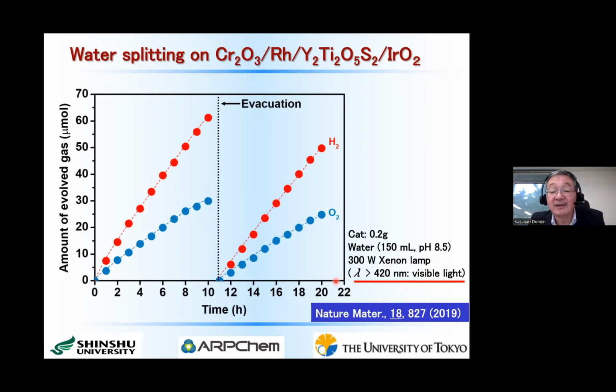However, as you see here, when we continue the reaction for 20 hours, the activity decreased to about 80%. But this degradation is not really due to the degradation of these oxysulfide materials, but our iridium oxide oxygen evolution co-catalyst seems to be degraded because, as I said, we just adsorbed this iridium oxide nanocolloid onto this surface. So we probably need to improve our preparation procedure of the co-catalyst. And another problem is that at 420 nanometer, the apparent quantum yield still remains at about 0.36%. So again, we still have a lot of room to improve the activity.